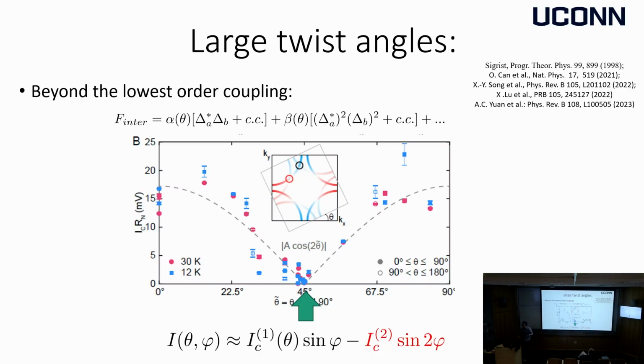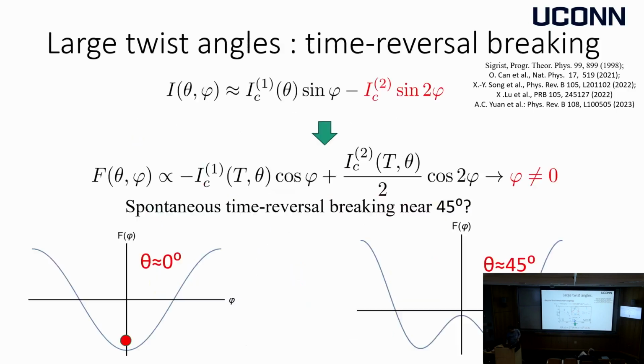By itself, it just tells you that there would be some superconductivity across the interface, but you can also relate it, as I did a few slides ago, to the energy stored in this junction as a function of phase difference. And while the lowest order term, cosine phi, always favors the phase difference to be zero across the interface, which kind of makes sense, you want to have a uniform superconductivity, the second order term, dominating at 45 degree, actually favors a non-zero phase difference, and if you cross out this term, the phase difference that is favored would be plus or minus pi half.